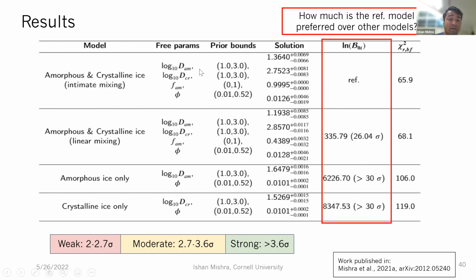And here's the key result from our analysis of that mean Juno spectrum. We compared four models. The first is two kinds of water ice intimately mixed together, so they're well mixed. Secondly, they exist as different patches. The third and fourth models were just one component each, so the second kind is not present. This is the model comparison metric, where these numbers tell you how much more the reference model is preferred over these models. It's a ratio of the probability of the reference model over the other model, so the larger this number is, the more the reference model is preferred. You can see that clearly the intimate mixing model was preferred, with very high significance compared to linear mixing or the one component only models.